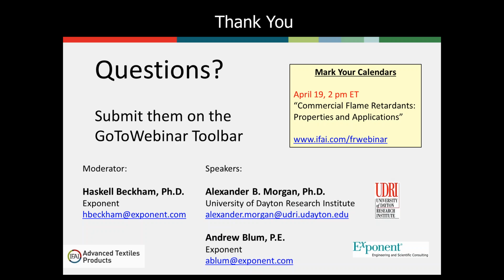Yeah, and one thing that I found too, Alex, is that even if you're not going through the painstaking motions of correlating perfectly to an end result with the E84, just having a material, for instance, that can pass E84 and burning it in the cone, and then burning some new research materials, something that they're just working on, and getting an idea of how that material compares to the baseline one that passes, can at least give the manufacturer an idea of what they're doing. If they find, wow, we've got a much higher heat release rate with this new material, this might not perform as well in E84. That at least gives them a heads up moving forward. Yes, I definitely agree with that. That's very much how I sometimes guide my customers when they submit samples. Yes, right. That is a fair assessment.